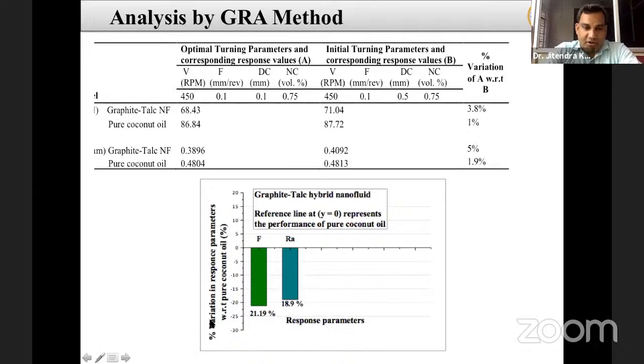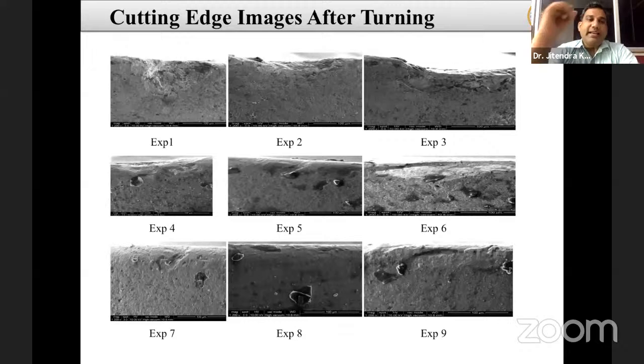So we plotted the percentage variation with the response parameter and obtained that the cutting forces vary by 21.19% and the surface roughness by 18.9%. This is the variation with the pure coconut oil compared with the hybrid nano cutting fluid. The cutting edges we also see by SEM micrograph, scanning electron microscopy.